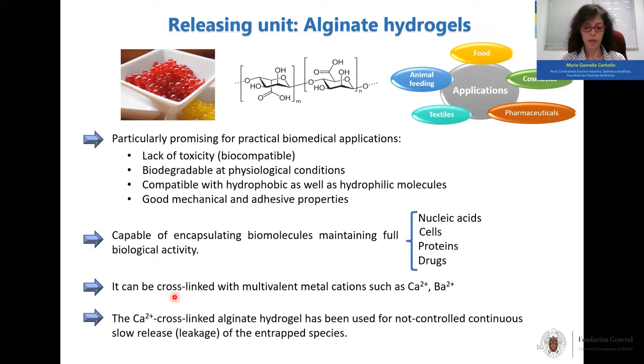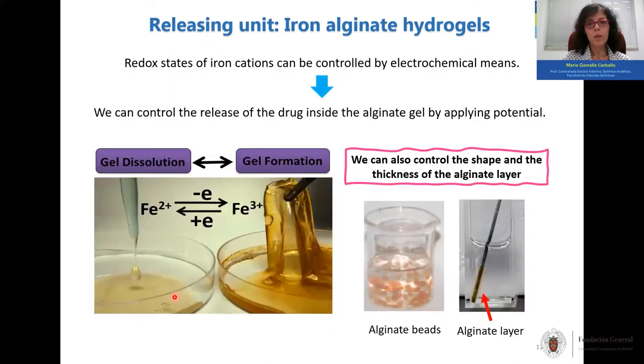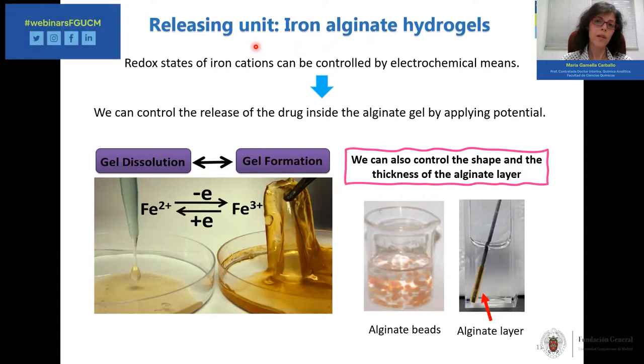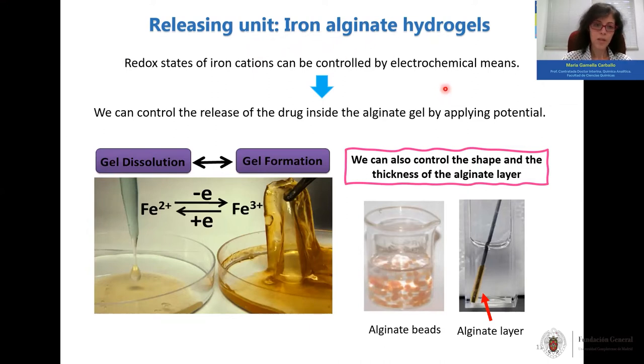Specifically, calcium cross-linked alginate has been used for the non-controlled continuous slow release, also called leakage, of different molecules in pharmaceutical applications. However, we didn't want to have this uncontrolled release. We wanted to control the release. In order to achieve this triggered signal release, we prepared a special kind of alginate hydrogels using iron as crosslinker. These iron cross-linked alginate hydrogels present an advantage over the calcium hydrogels because it's possible to control the formation of the gel and the dissolution depending on the oxidation state of the iron.